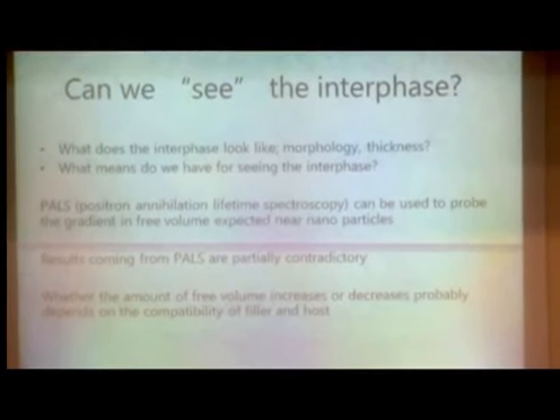Some people see the amount of free volume, from which the thickness of the interface can be calculated, grow. Some of them increase. Some of them see it as decreasing. So what to think about that? It is clear, however, that the way we made the nanoparticles compatible with the host material has a strong influence on whether we get an increase or decrease in free volume.